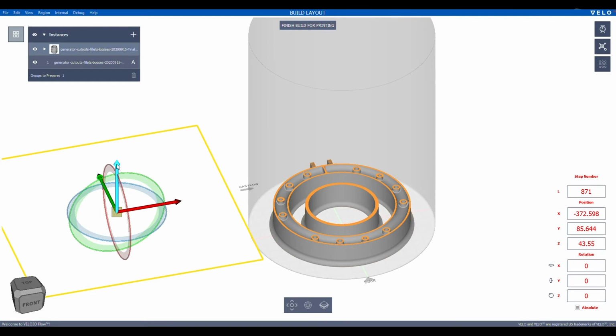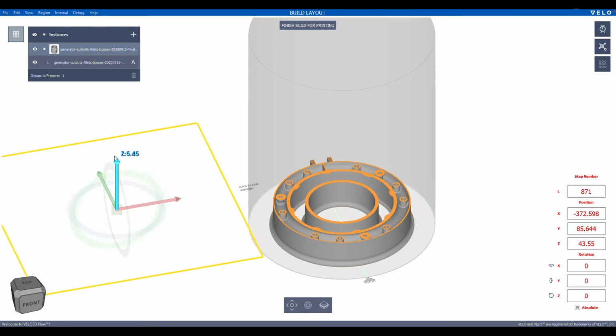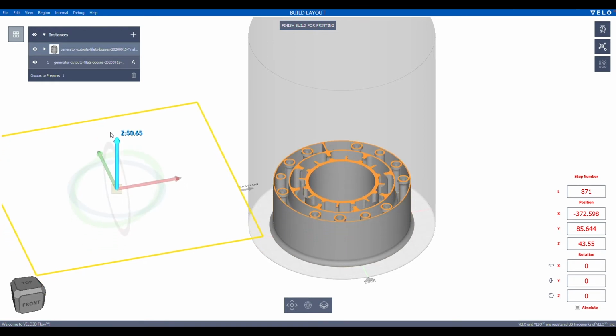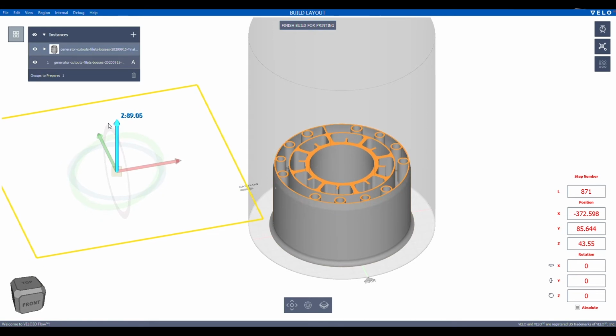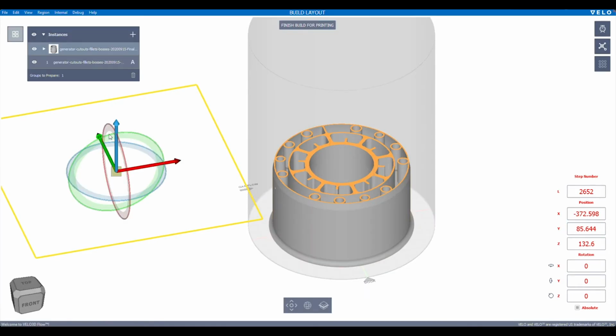The walls are pretty thin. They start to get pretty tall, especially these internal bosses and tubes, which can be subject to recoater interference. As they get very tall, they get flimsy, and any lateral force could move that thin structure around. On a conventional metal AM printer, that might be problematic. It's just something that we don't have to worry about because of that non-contact recoater.